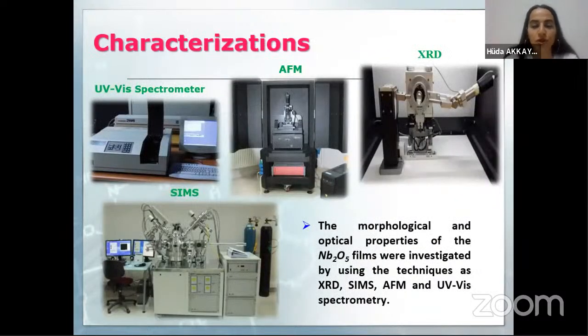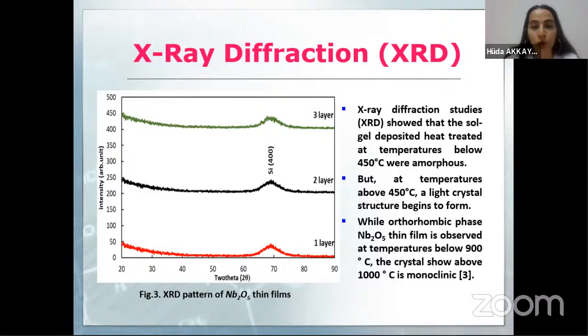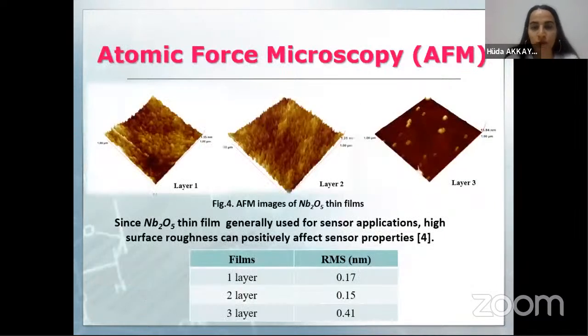Characterization. The morphological and optical properties of the niobium pentoxide films were investigated using UV visible spectrometer, atomic force microscopy, X-ray diffraction, and secondary ion mass spectroscopy. In X-ray diffraction, all niobium pentoxide films had an amorphous structure. For niobium pentoxide to begin to crystallize, we have to heat it above 450 degrees, but in this study we dried it on a heater at 120 degrees. The orthorhombic phase of niobium pentoxide thin films is observed at temperatures below 900 degrees, and the crystal shows monoclinic above 1000 degrees.